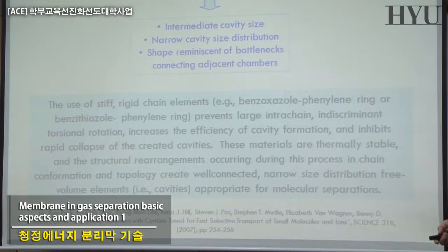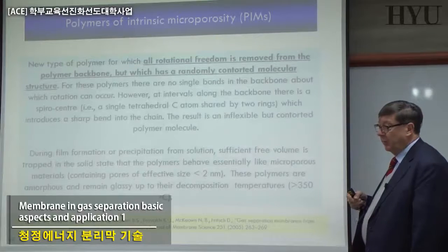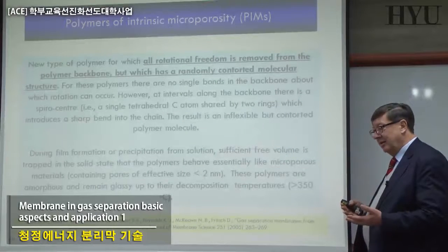Basically, you can have this final morphology, and at the end you have well-connected, narrow size distribution free volume elements, which are interesting for the kind of separation of interest. A lot of work has been done, and this material can be just one of the new kinds of material in which you don't change anything, there is no addition, there is no mixed matrix, etc., but you are inducing what we also call a post-treatment of your polymer.